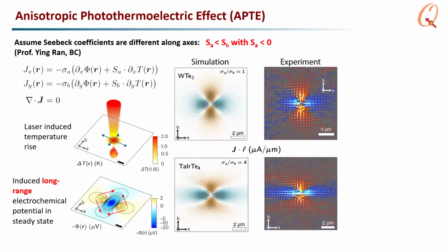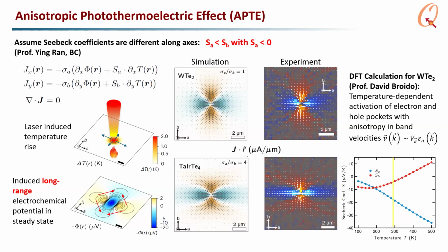And then we can simulate this. We can simulate this model using conductivity parameters for WTe2, and it very much agrees with the experiment. We can also look at tantalum iridium tellurium-4, which has more anisotropic conductivity, and it matches our data really well. Then you can go to DFT calculations, and indeed DFT calculations predict that the Seebeck coefficients should be different along the 2 axes. This is due to the fact that these are type 2 Weyl semimetals, so you have both electron and hole bands, which can give you different signs of the Seebeck coefficient depending on their band velocity in the different directions.